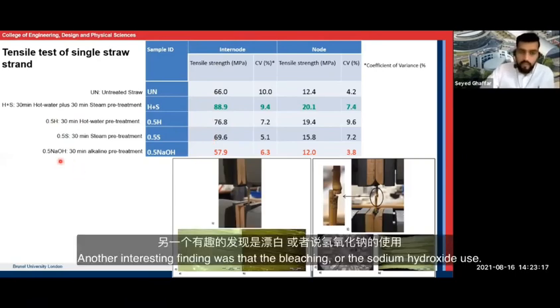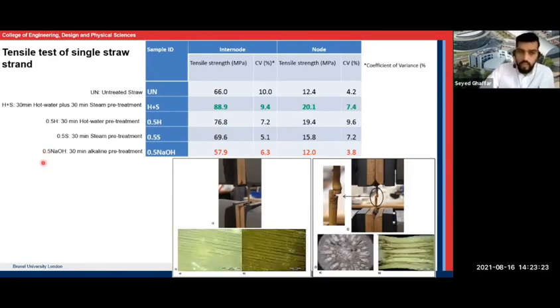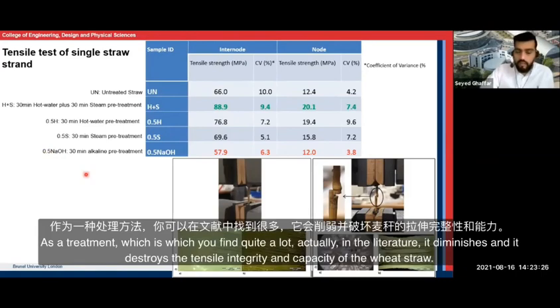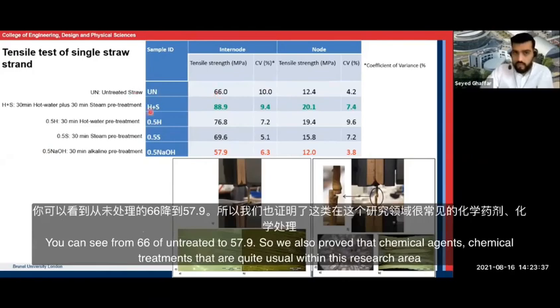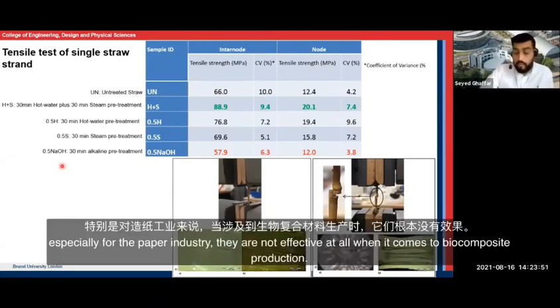Another interesting finding was that the bleaching or the sodium hydroxide used as a treatment, which you find quite a lot in the literature, diminishes and destroys the tensile integrity and capacity of the wheat straw. You can see from 66 for untreated to 57.9. So we also proved that the chemical pretreatments that are quite usual within this research area, especially for the pulp and paper industry, are not effective at all when it comes to biocomposite production.